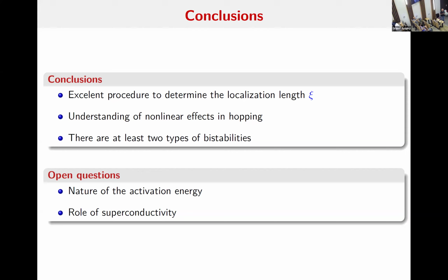Okay, I never thought about this, but yeah, you may be right. The grains are probably disordered. And to answer your first question, we see a difference when we go closer to this superconductor. From a purely activated behavior to an activated behavior but with a different activation energy, which we interpret as the beginning of some kind of superconducting gap. So like superconducting islands, and then you're hopping between the islands. Then these other components also get modified.